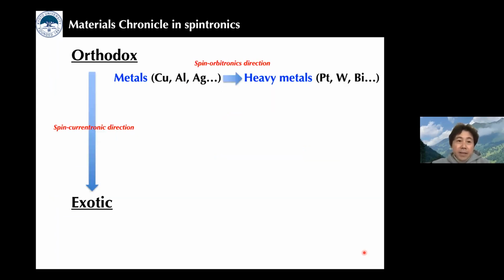So here in this slide, I show the materials chronicles in spintronics. In the first generation, people focused on the metallic materials, for instance, copper, aluminum, and silver. And along the spin orbitronics direction in the third generation, heavy metals become much more important. Here, I mean the heavy metals to be platinum, tungsten, bismuth, and so on, because they have a sizable SOI, which allows efficient spin conversion.